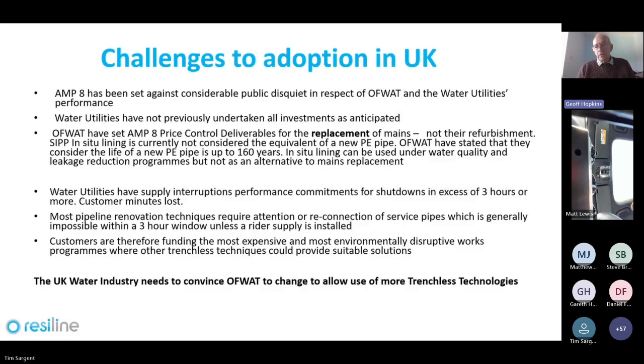In situ lining can be used under water quality and leakage reduction programs, but it's not an alternative to mains replacement. And the other fundamental issue at the moment is this 3-hour customer lost minutes shutdown period. If you start putting higher build linings on, or higher build renovation techniques, you've got to start reconnecting service pipes, and that's generally impossible in a 3-hour window. So what the water industry needs is to convince Ofwat to change the current financing regime and operating regime to allow more use of trenchless technologies. That sums up my statements. I'm sure Steve will have more to say on that later.